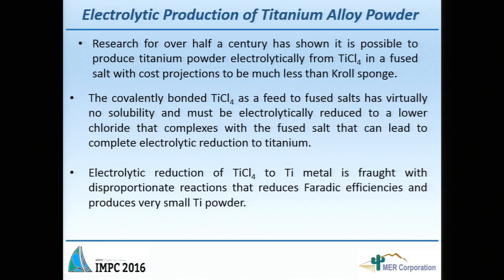So I think the previous speaker mentioned that there was a lot of effort on electrolysis of TiCl4, almost half a century, I think since the 70s. And there was indication that it's possible to produce titanium powder from TiCl4. But a couple of the problems, in addition to the different oxidation states for titanium, is that titanium tetrachloride doesn't dissolve very well in molten salt. So you have very limited solubility because it's covalently bonded. So you're starting already negative in terms of the concentration of titanium in the electrolyte.